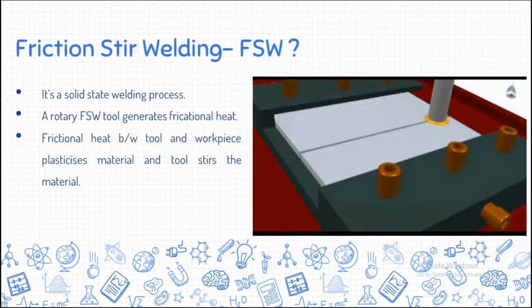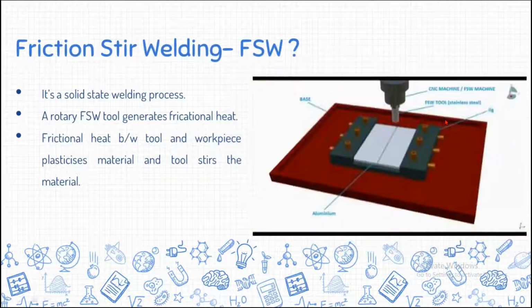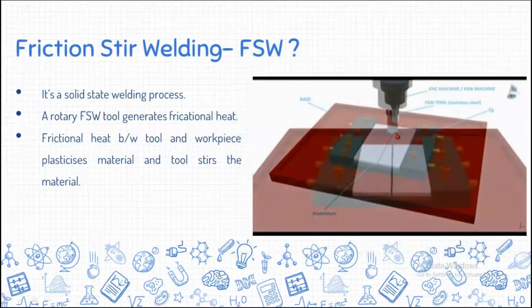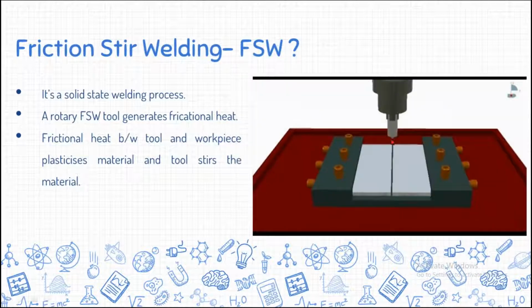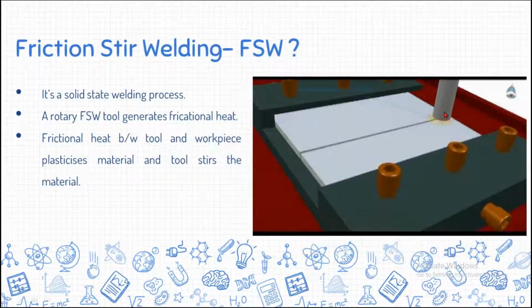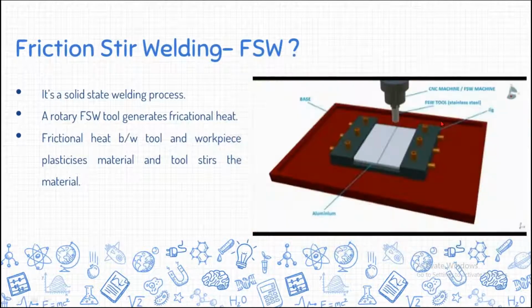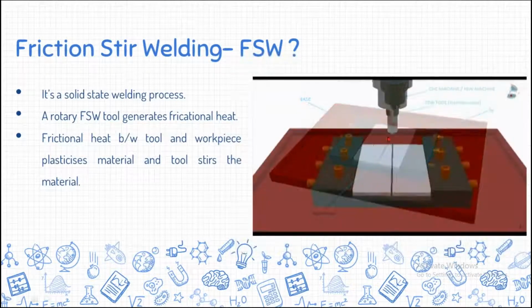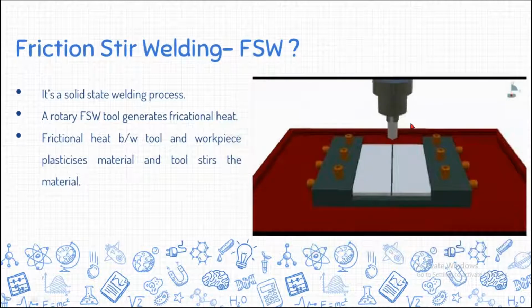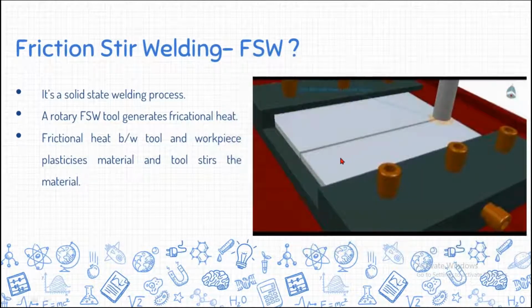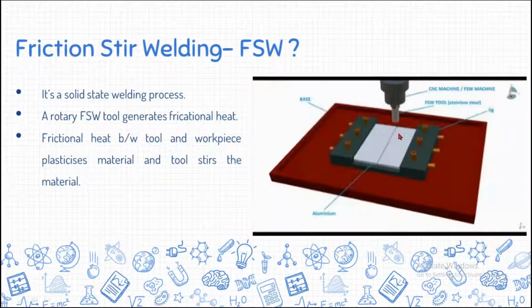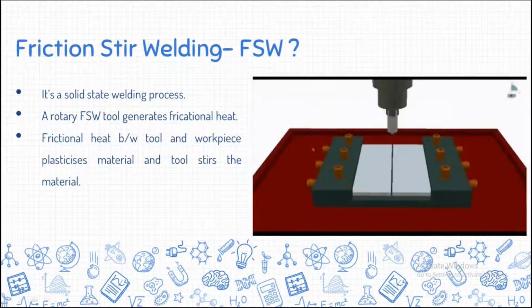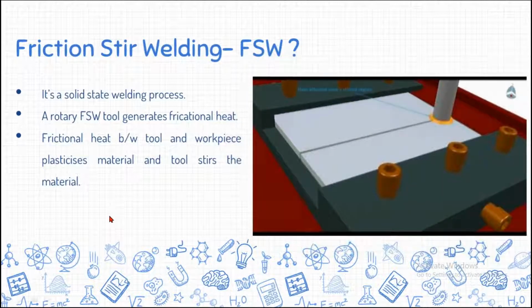Here, what happens? A tool rotates and plunges into the two welding plates. Once it completely plunges into the welding plates to some extent, due to the interaction of this tool with the workpieces, this rotary tool rubs on the surface of the plates. This rubbing action creates friction. This friction is the source of heat in this particular process. So this rotary tool plunges into the workpiece and traverses along the welding line, and due to the heat, the material plasticizes. This stirring, rotating action mixes this plate and this plate together, and during the solidification, during the cooling time, the welding occurs. That is what happens in this particular process.